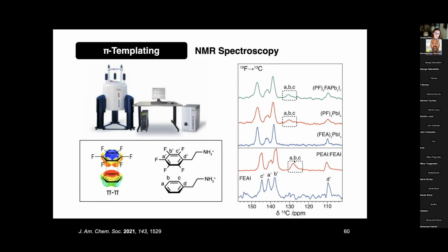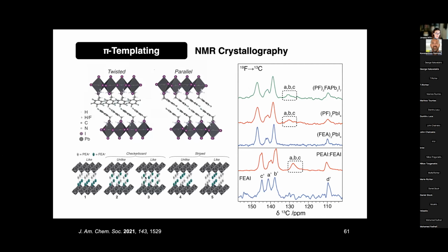However, if we more critically assess these spectral characteristics, we also see that the mixture of the two spacers features very comparable spectral characteristics in this aromatic region to the purely perfluorinated system, suggesting that perhaps this nanoscale proximity could also be the result of nanoscale segregation instead of a bulk alternating fluorinated, non-fluorinated pi templating effect. And to scrutinize this more critically, we complement this analysis once more with an NMR crystallography approach, looking into a number of different configurations, some of which are illustrated here, including this fully alternating layered system, including both aromatic and perfluorinated systems, checkerboard-like structures, or this kind of stripe-like assemblies, considering both twisted and parallel orientations of the corresponding spacers that